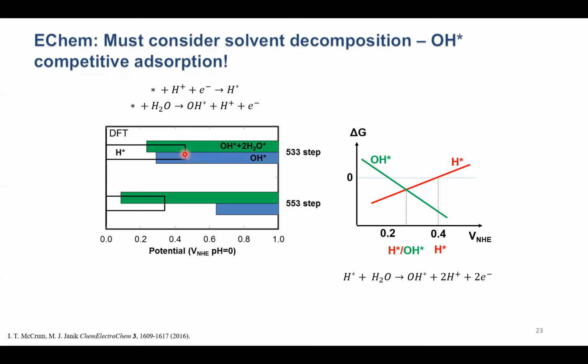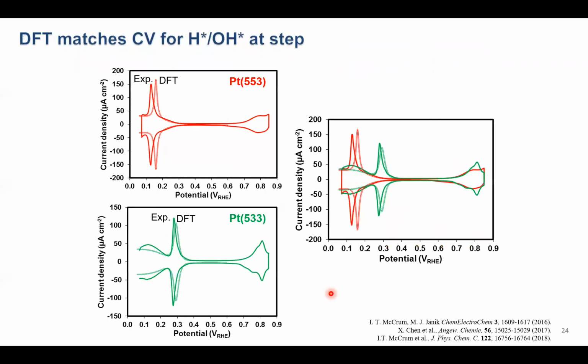And what we see on the platinum steps, at least if we consider co-adsorbed water with that hydroxide, is that these two curves overlap. And so now the peak that we measure in the CV is not going to be where hydrogen adsorbs. It's going to be where we see this exchange between adsorbed hydrogen and adsorbed hydroxide in water. And so now if we simulate cyclic voltammograms considering this exchange, we find that they do in fact now match experiment. And so here we see a broad peak for adsorption on both surfaces that's due to hydrogen adsorption on the terraces. I didn't really talk about that, but that matches experiment quite nicely.